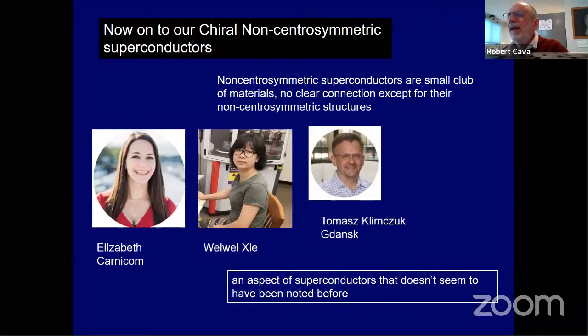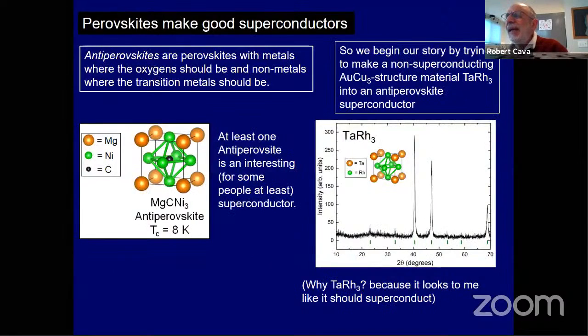Okay, so superconductivity in the BCS picture is just a sea of electrons that interacts, the way I look at it, with a sea of phonons that come from some crystal structure. But then, if you have a non-centrosymmetric crystal structure, you have K and minus K in reciprocal space not equal to each other. I always think of reciprocal space. You might think of it as K space, whatever, but they're not the same. So the pairing has got to be different in something that's non-centrosymmetric. But there's more to it than that. And I'll tell you the story of how we found this one.